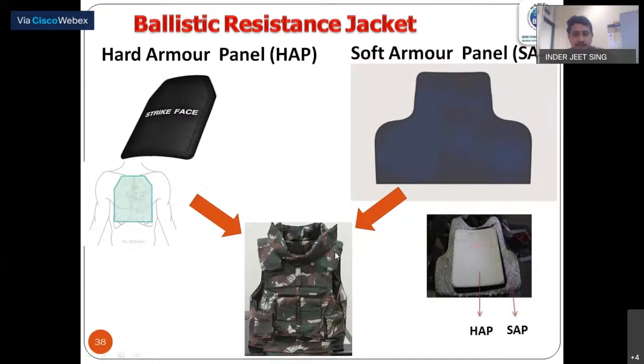So what happens? We wear this jacket. All these things are soft armor material, and this hard armor panel is the insert inside this pouch. So for low caliber bullets like a 9mm bullet or whatever is fired from a machine gun or Sten gun or pistol, that can be stopped by the soft armor panel itself, which is called SAP. But for higher caliber bullets like AK-47, INSAS and SLR, you require this hard armor panel, which is put into the insert front, back as well as sides wherever required.